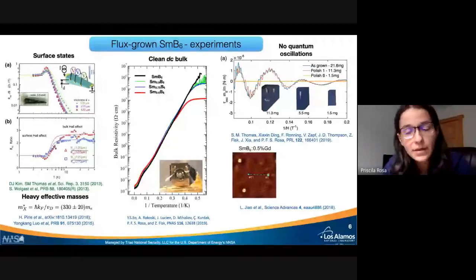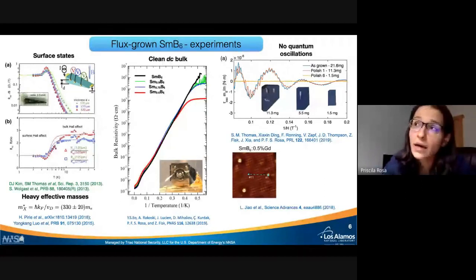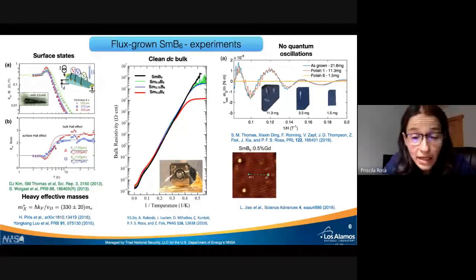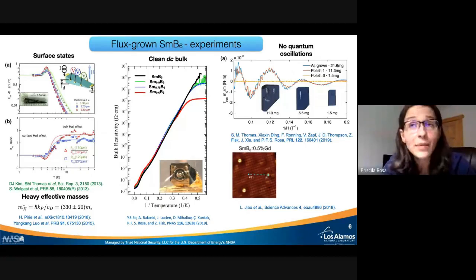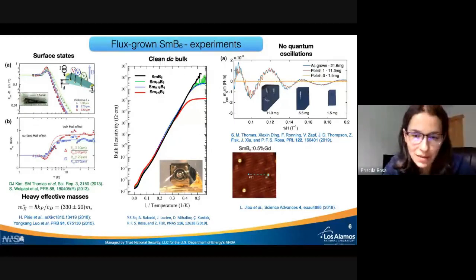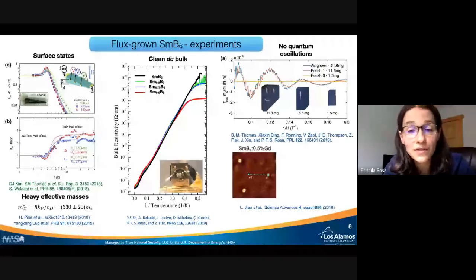Well, if you remember from before, from the first slide, we have a topological insulating state, and that surface state is, in particular, protected against backscattering that preserves the symmetries of the system. In this case, gadolinium has a moment, so it has magnetism, it has a large spin, and that breaks time reversal symmetry. So you're not preserving the symmetries of the system anymore, and you would expect the surface states to be affected by those impurities.